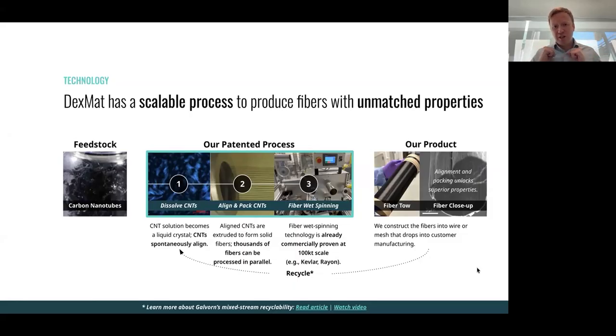But when we push this liquid crystalline solution through a series of small holes that looks like a shower head, called a spinneret, we cause all these domains of liquid crystalline nanotubes to align in one direction. And then, in step 2 of the process, they get densely packed together, and we push them through a coagulating liquid bath that removes the solvent and causes the carbon nanotubes to coalesce and lock in that highly aligned structure where they're all oriented in the same direction and densely packed. Then we wind up the fibers onto rollers at very high speeds, at which point they are now 100% carbon nanotubes, with some steps to remove any excess solvent.